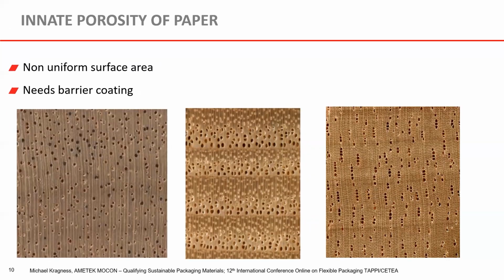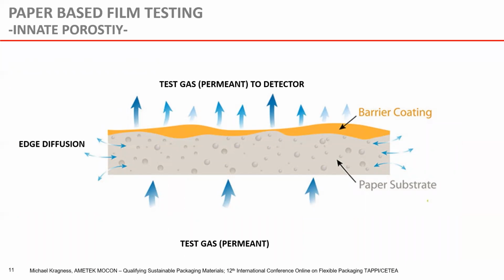Now let's move on to paper. This is the broad subject of this presentation, because paper, as you can see by these photos, has a lot of porosity, and from that porosity, the structure contains a lot of extra surface area. So you can't just use wood or paper as a barrier, because it's porous, right? You have to coat it somehow to make it a barrier. Looking at this example, it's a paper substrate with a barrier coating. On one side, we're challenging this sample with a test gas, let's say moisture. That moisture moves into the paper substrate, and then permeates through the barrier coating onto the other side, where we can quantify how much moisture actually permeated through this material.